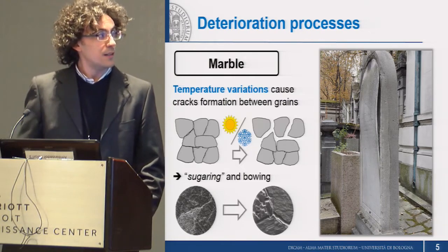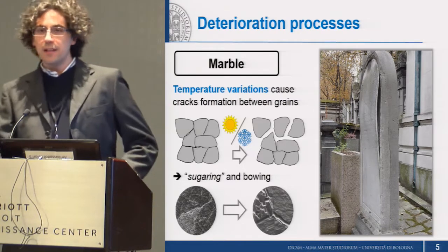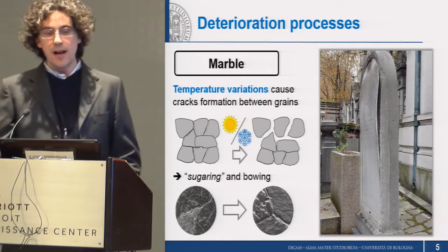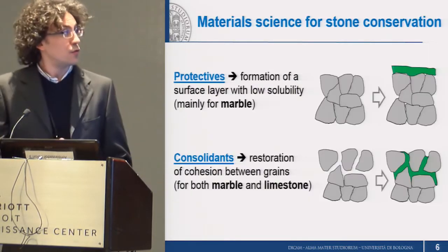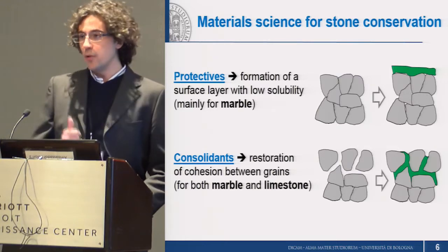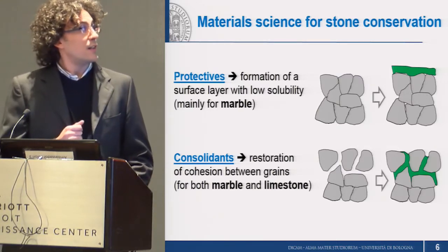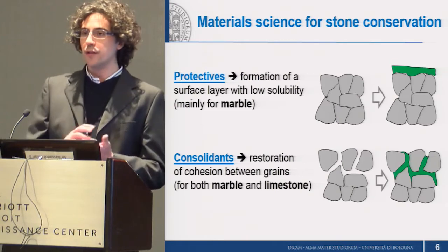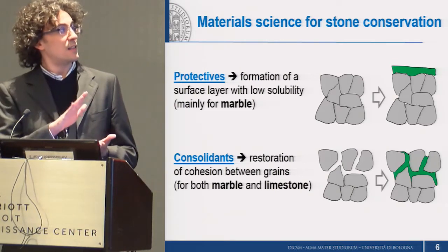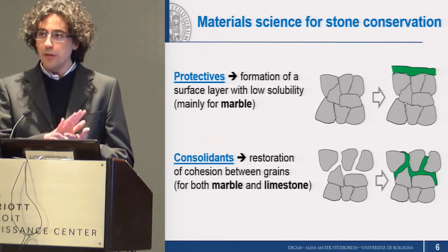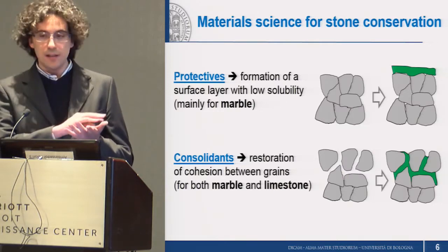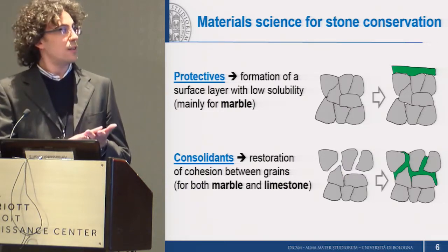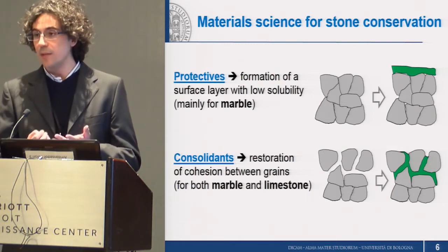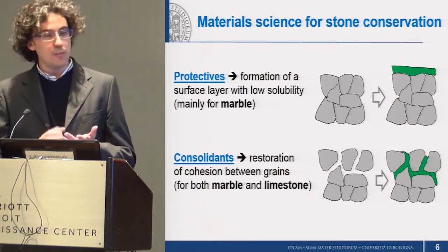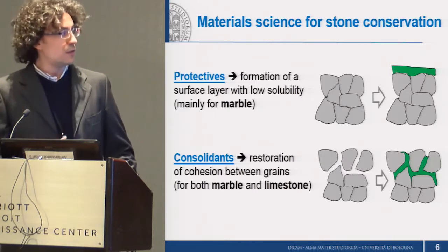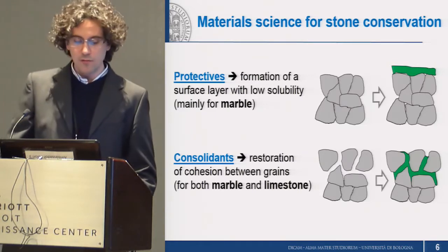So the basic aims of material science applied to stone conservation are these two: developing suitable protectives and suitable consolidants. Protectives are products, materials, that are aimed at bonding tightly to the substrate and creating a surface layer, a surface coating, that has a lower solubility than the substrate, so that this layer is able to provide protection against dissolution in rain, especially acid rain.